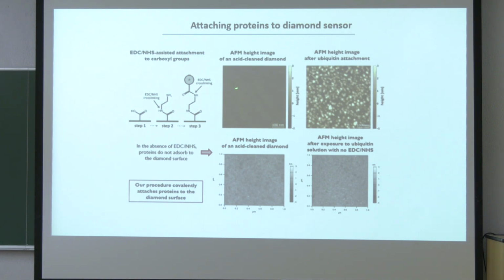And so here on the right side you see AFM pictures of diamond showing very flat topography before attachment of molecules, and a rough surface with a nanoscale roughness, typically corresponding to the size of this protein, after chemical attachment of the protein. So you can create close to a monolayer of this molecule, and you can now think, well, maybe it's not single molecule detection, but remember that the NV center sits so close to the surface that it sees only one of these molecules, even less than a whole molecule. Only a fragment of the molecule will be seen by a single NV center.